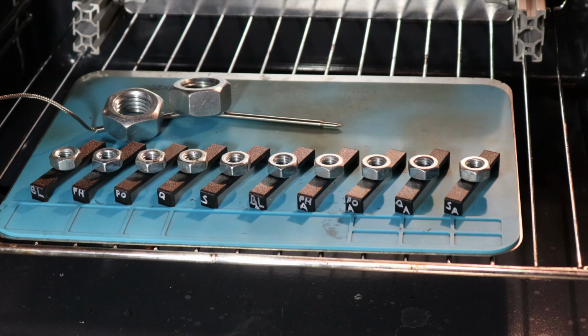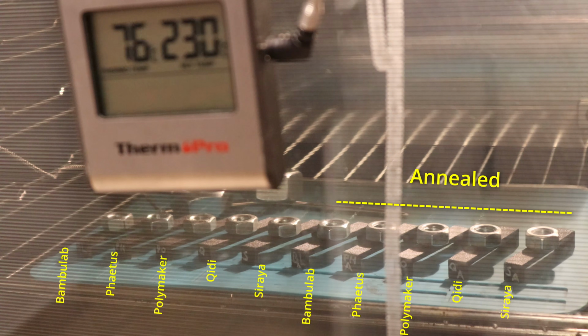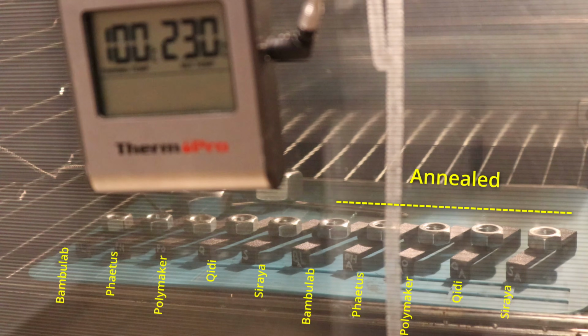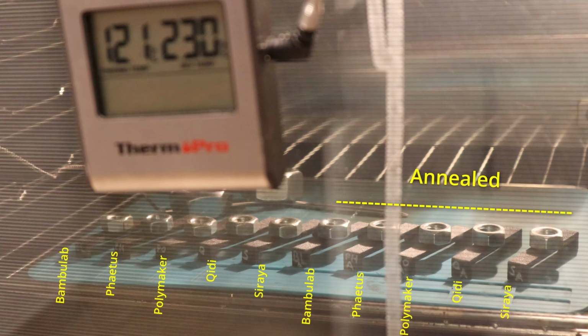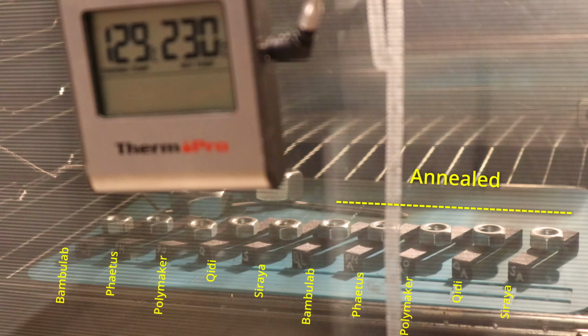Temperature test in the oven. 5 on the left are regular and 5 on the right are annealed, and both in ABC order. 5 samples on the right didn't start to deform at all during this experiment. 5 samples on the left did begin to deform, but at different temperatures.